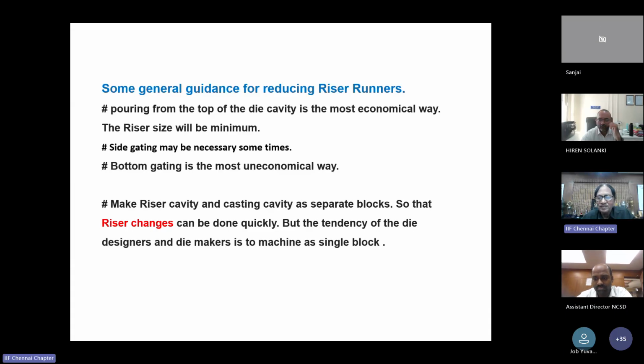Make the riser cavity and casting cavity as separate blocks in the die. Supposing you want to modify the riser, that riser cavity alone can be made separately. But the tendency of the die designers and die makers is to machine the die as a whole, that is, the riser cavity, the runner cavity and the casting cavity in one block. It will be very, very troublesome for any changes.